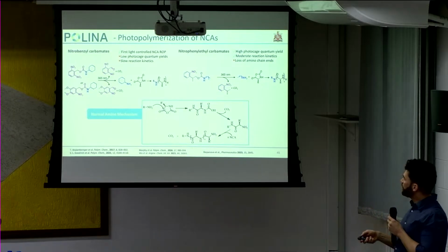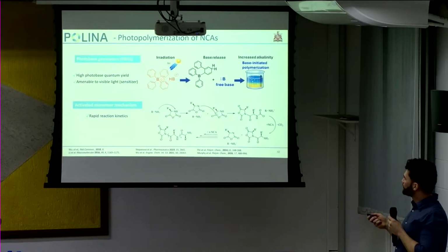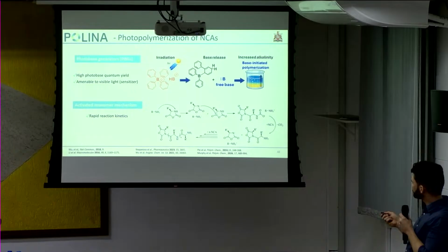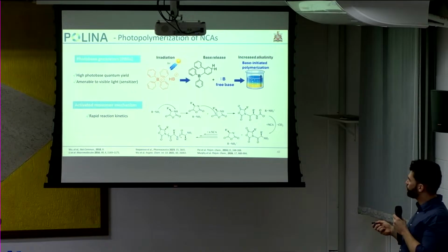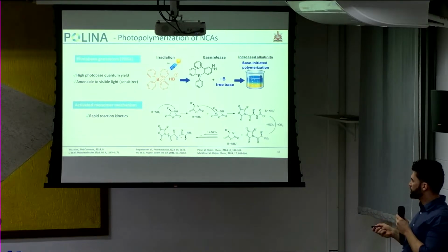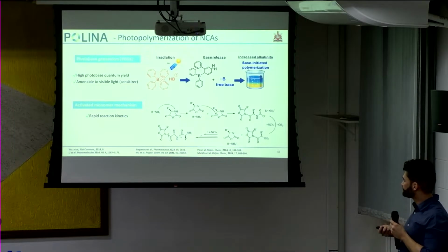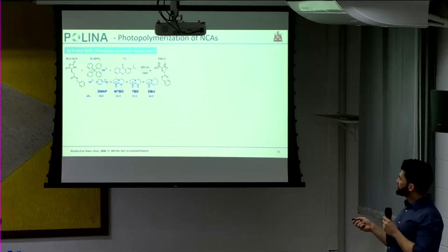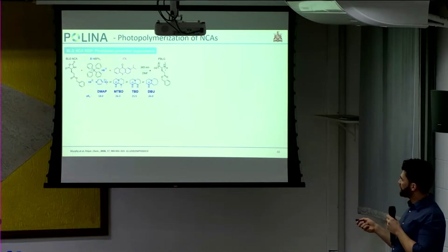So we started, in collaboration with our collaborators from Spain, using photobase generators, which have a higher quantum yield and are able to release a base in the system when irradiated with light, and are amenable to visible light as well with the addition of a sensitizer. And this free base here is a non-nucleophilic base. So instead of the normal amine mechanism, we have an activated monomer mechanism with much more rapid reaction kinetics. We started the study using BLG NCA because it's simpler, easier to make, and also stable.